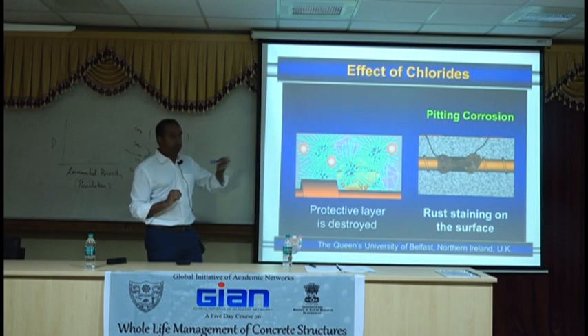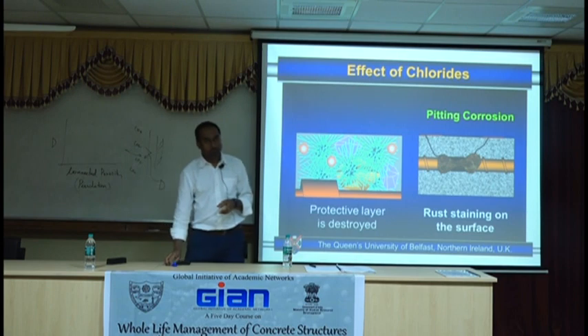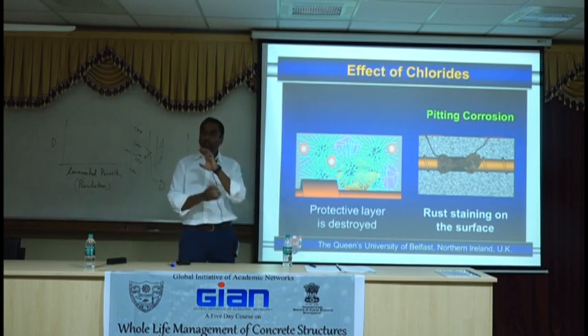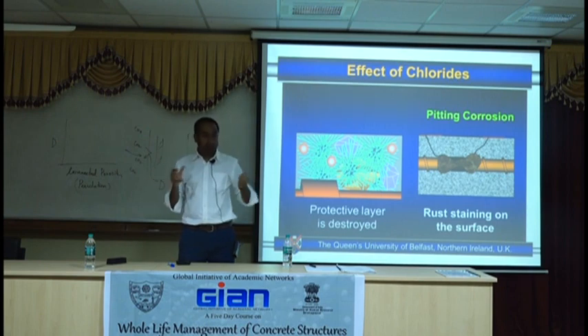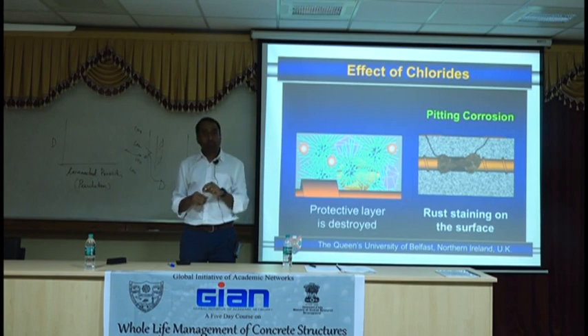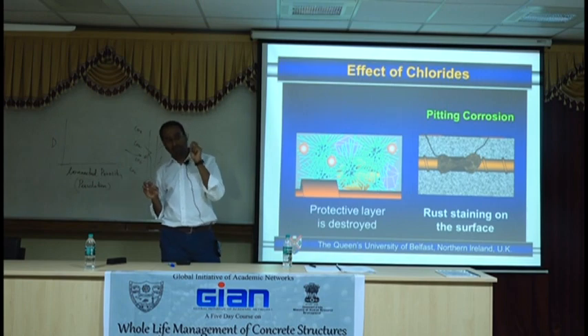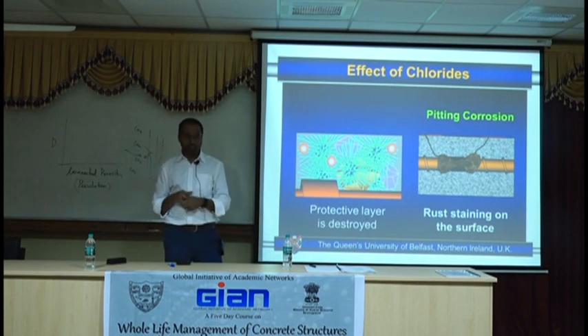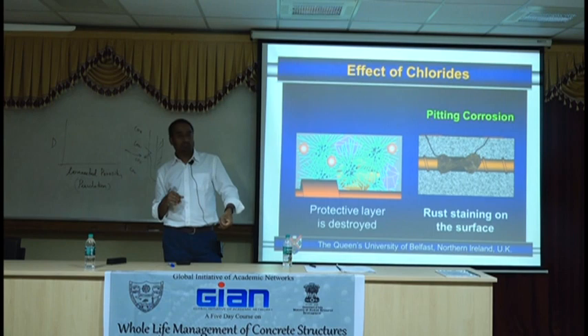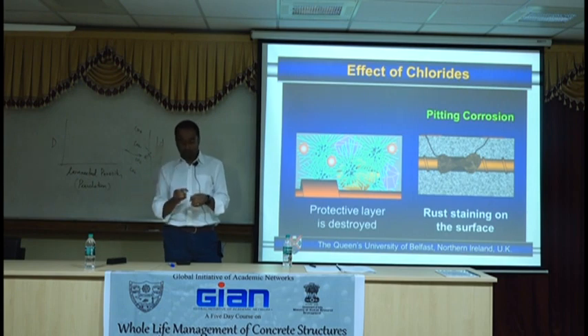Structurally speaking, if the integrity of the steel... so for structural engineers, we know that if the steel is damaged, if the amount of corrosion in a steel can be quantified, let's say somehow, what's more critical for us is not the surface damage. What's very critical for us is the extent of damage on one particular location of steel. It's the area of cross-section of steel. So the problem with chlorides is that it's pitting corrosion. Very typically it pits the steel.